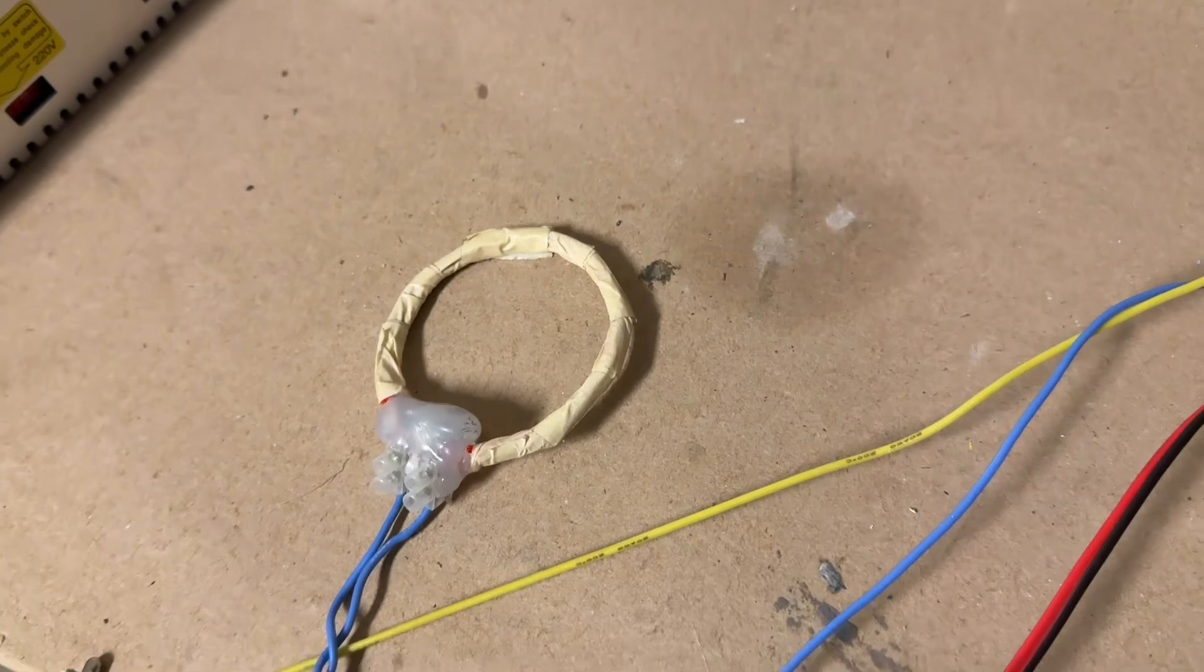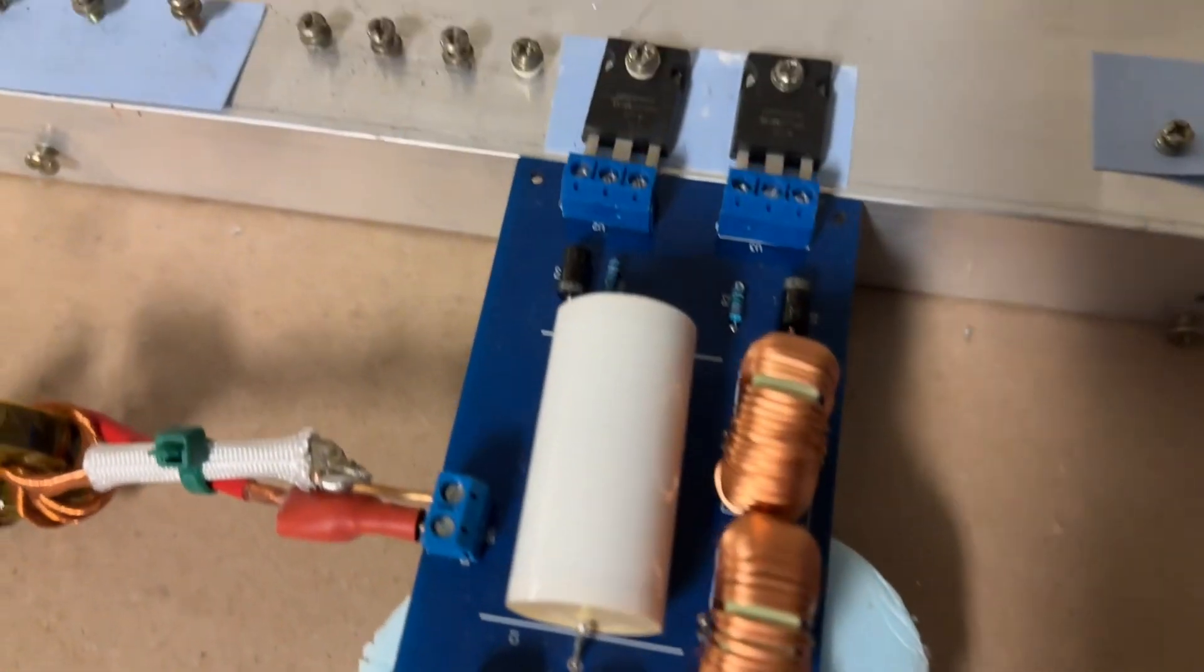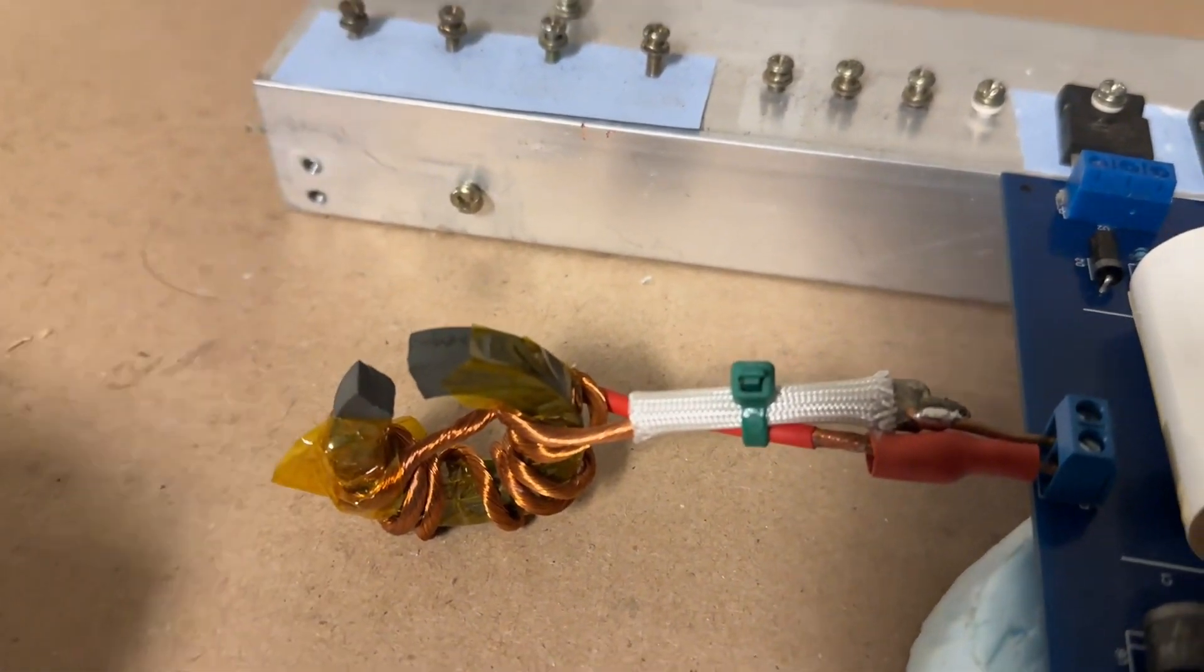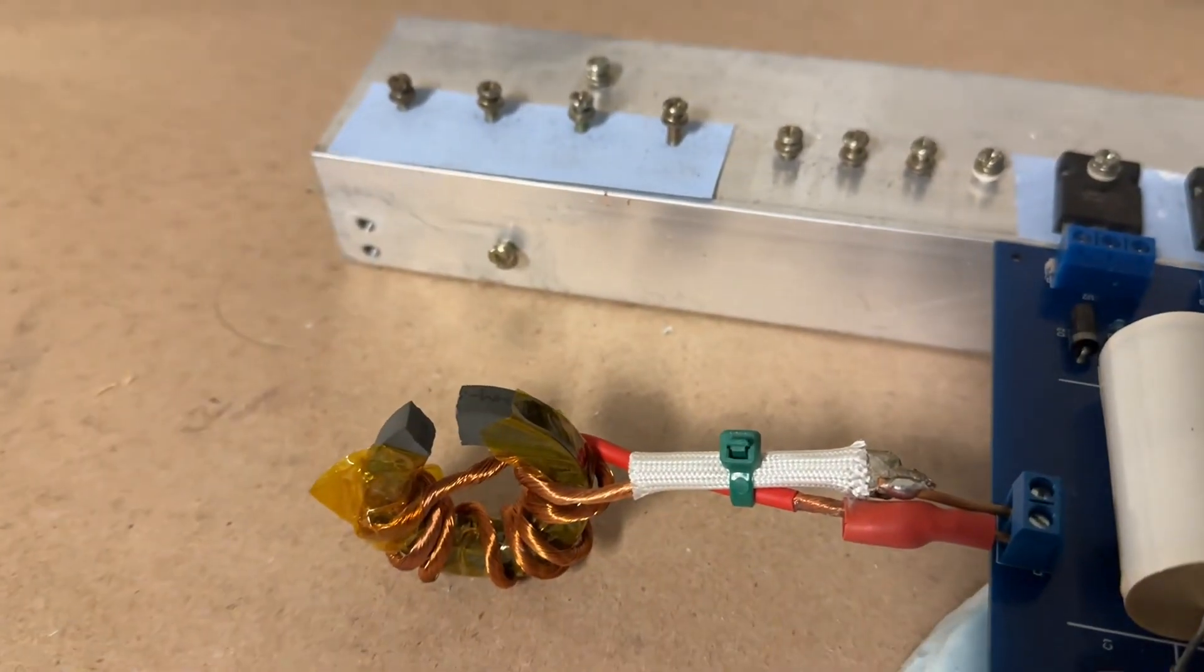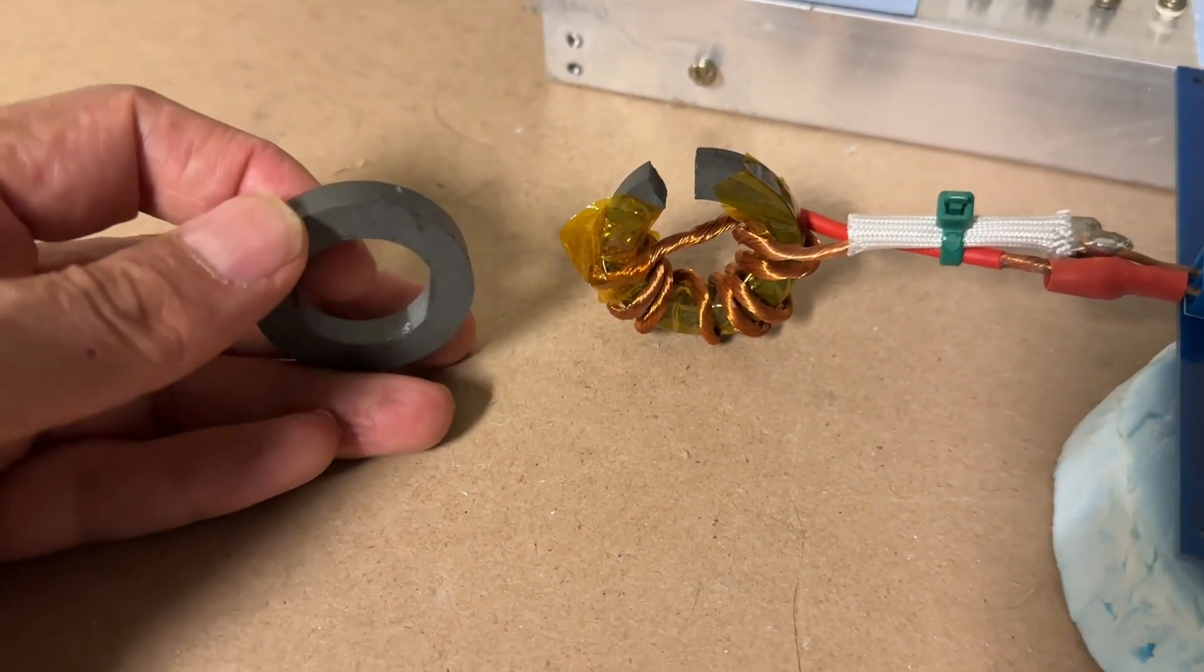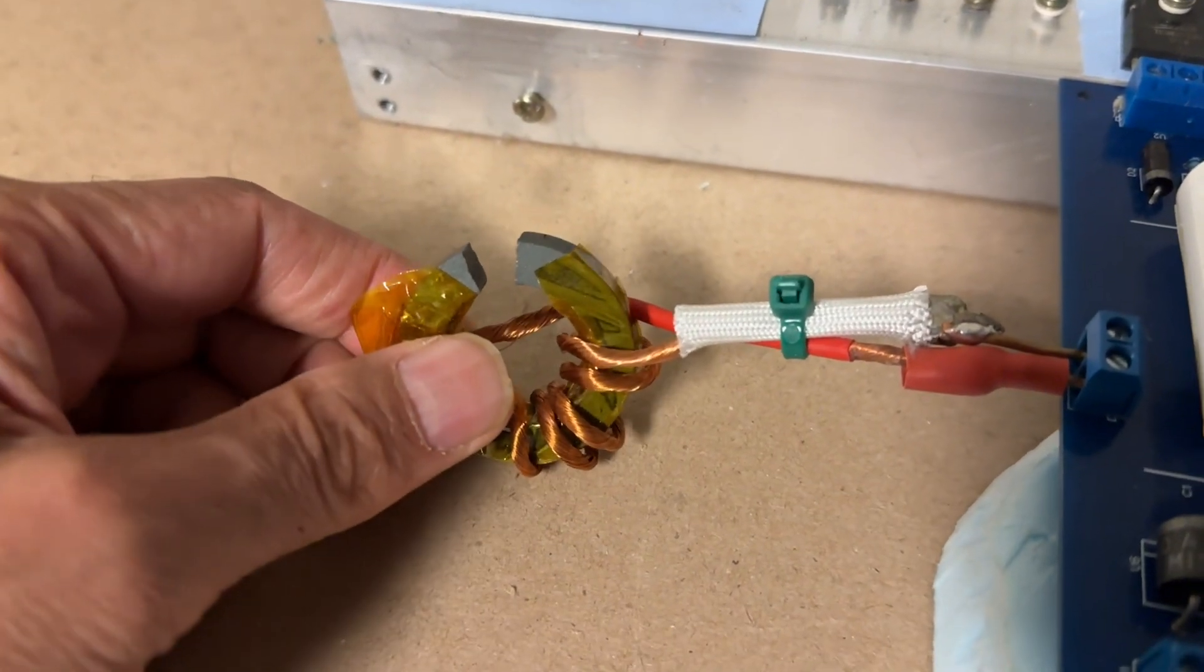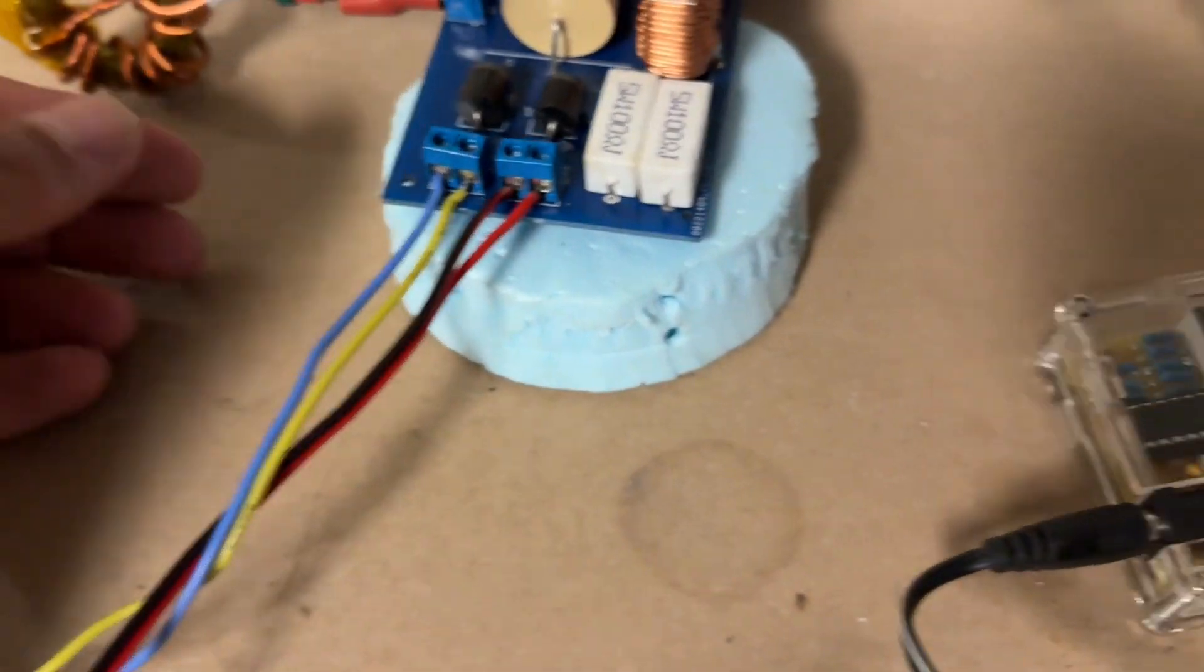I've got these on a heatsink and I'm going to turn on the gate supply. The gates should be running on this thing and there should be some oscillations happening in this ferrite. This particular ferrite, you'll notice there's a piece missing. I tried a full ferrite ring trying to induce oscillating magnetic fields in adjacent coils, but the ferrite rapidly heated up and fragmented. So I got a Dremel to another ferrite and cut out a little slot like this.